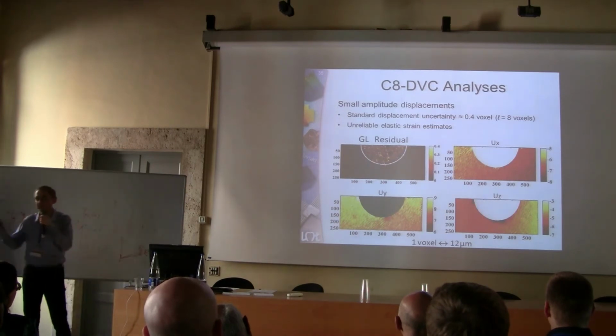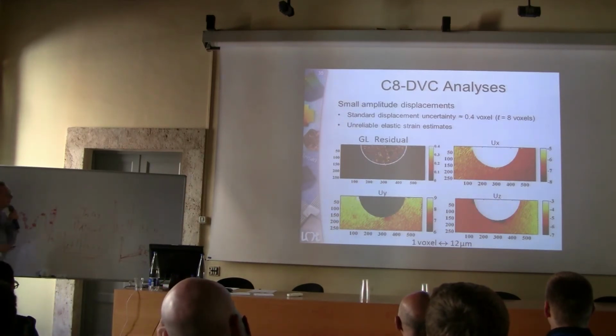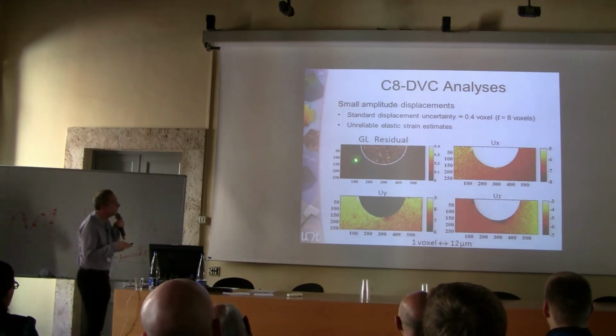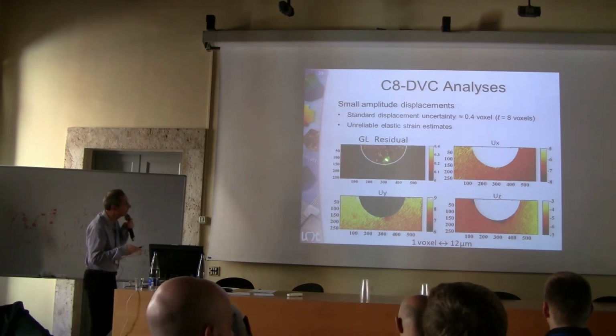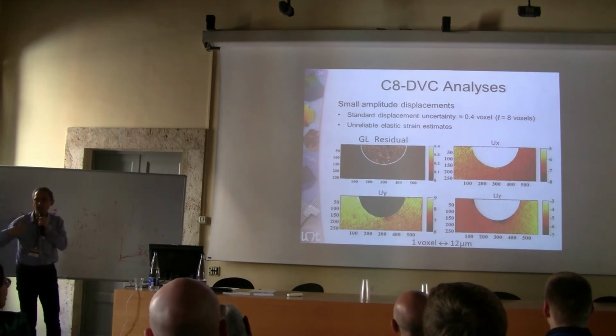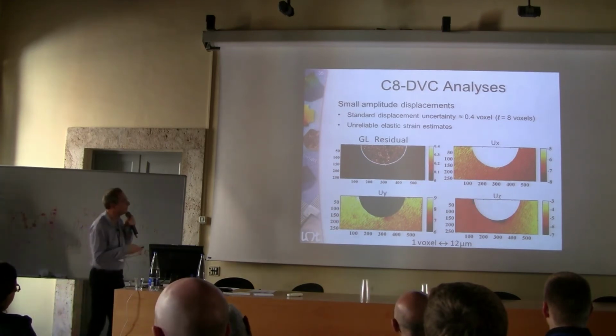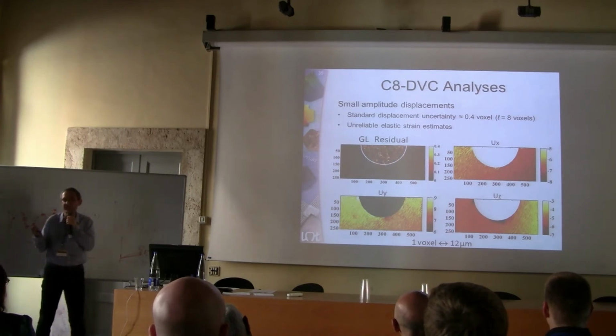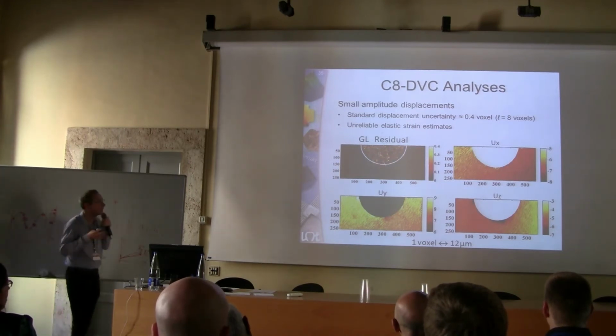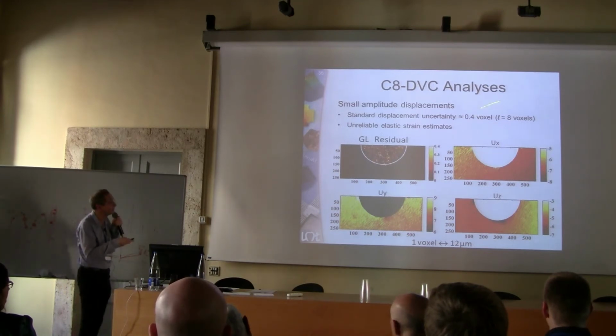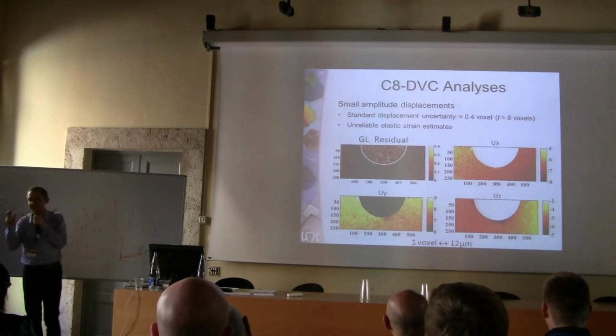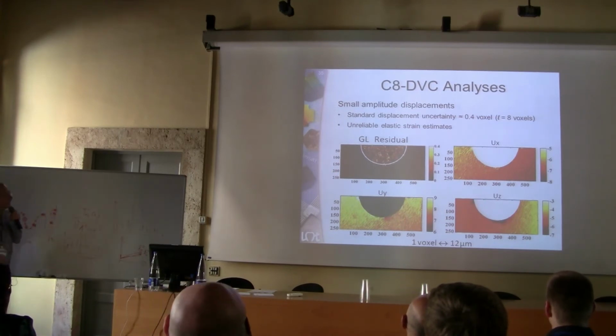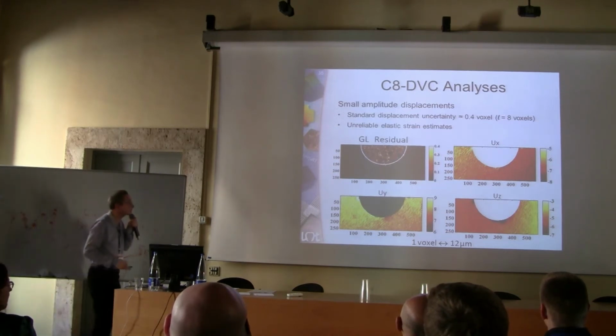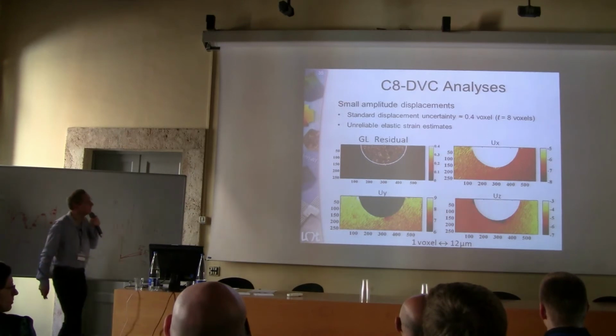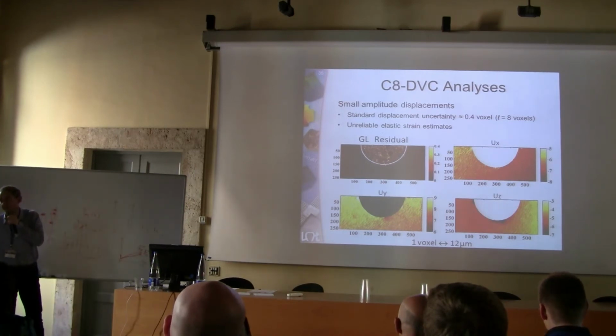Now, if you use standard DVC with a regular mesh, what we were really after was understanding what was going on between the undamaged, pristine material and the crushed material, which means you would like a very fine discretization. But if you take a very fine discretization, and in this particular case elements of edge size 8 voxels, that means the measurement uncertainty is on the order of 0.4 voxel, so there is no way you can reliably measure elastic strains.